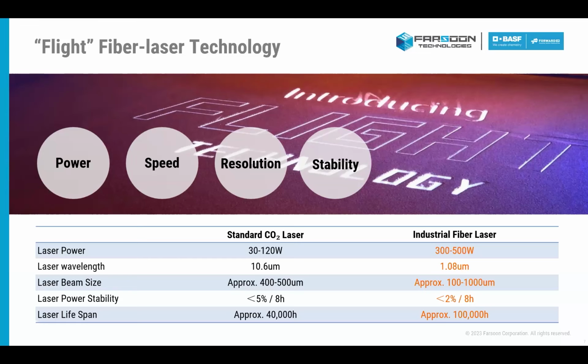And the last key difference between the CO2 and fiber lasers is their average lifespan and operational stability. So on average, a CO2 laser has a lifespan of approximately 40,000 hours. This kind of averages out to about 3 to 5 years of operational use, depending on power usage. So the higher you fire a laser continuously, the less overall life it's going to have in the system. The power stability of the laser, how much it drifts during operation, can reach upwards of plus or minus 5% during extended continuous use. But on the other hand, a fiber laser, because of its unique construction, has an average lifespan of about 100,000 hours, or about 10 years. This significantly increases the value of the machine, reduces maintenance and replacement costs of multiple CO2 lasers over the same time period.